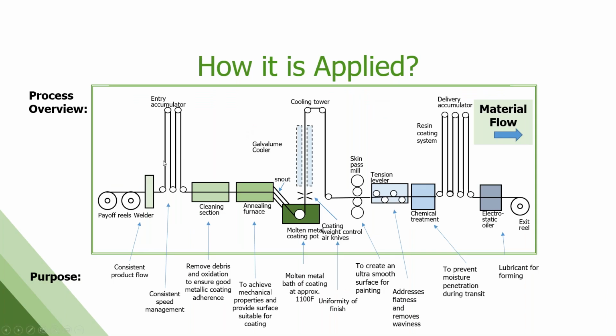This is a very generic schematic of a metallic coating line. We can put 2 coils on an entry on the left. These payoff reels, the ends are welded together, which allows us to run continuously. So there's always strip in the line. What these accumulators allow us to do is slow and stop sections while the rest of the line continues to move. Goes through a cleaning section, which is really important for aluminum zinc products versus galvanized products. Needs to be a much cleaner surface for good adhesion. Then goes through an annealing furnace, which is actually determining the mechanical properties of the steel. Doesn't really have anything to do with the coating that's going on it, but that's where you get your grade of steel. Grade 80, grade 50 probably being the 2 most common in the construction world.